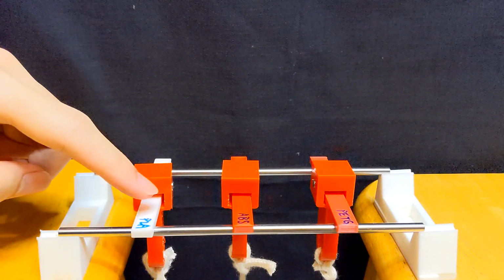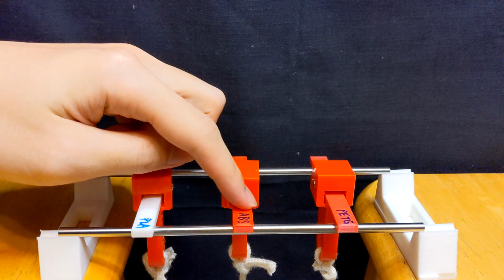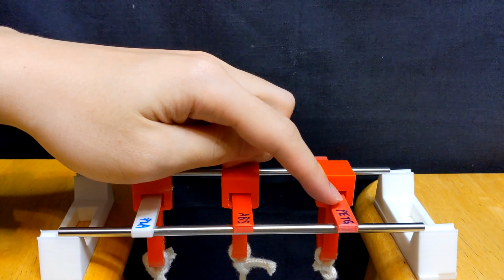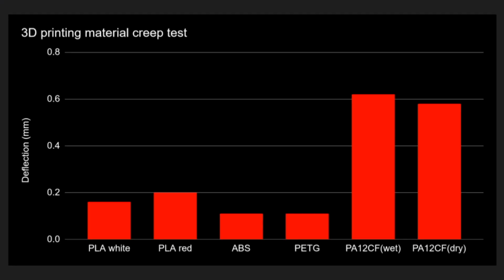After loading for several days, I used the dial indicator to measure the deflection of all the materials. Here is the diagram showing the details of all the test specimens. Although I was concerned that PLA creeps all the time and is not suitable for loading applications, the carbon fiber reinforced PA12 seems to be even worse than PLA. Only 3 days of loading caused obvious differences from the other materials.